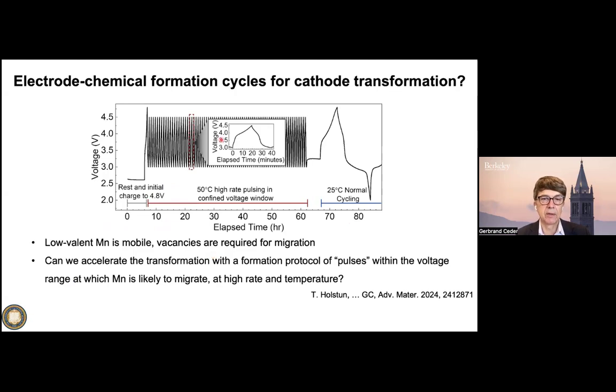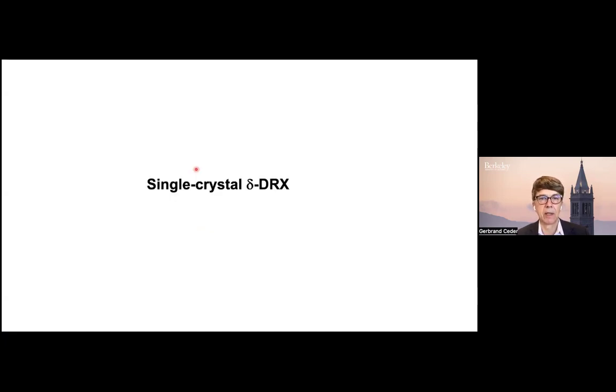So the way that's done is that basically you take the material and rather than cycling it, you give it a specific set of pulses. This isn't really the most optimized pulsing sequence that I'm showing. We do that at slightly elevated temperature, which is also typical for formation cycles. We do it at 50 C, but you could do it at 40 C, you could do it at 60 C. You pulse in a particular regime, and that pulsing regime is now close to optimized. And that actually causes the transformation. So by the time then you actually put the cell in use, you already have delta DRX available.